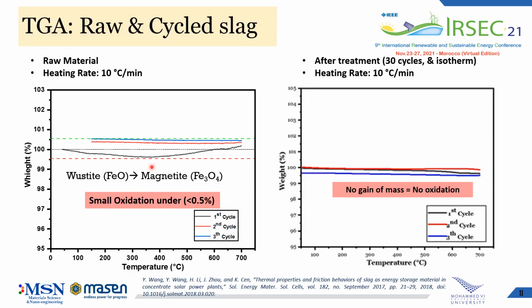And that was confirmed by TGA analysis, where we have a slight mass loss in raw material due to the evaporation of volatile compounds, followed by a gain of weight due to the oxidation of wustite phase. After thermal cycling, we didn't detect any significant gain of weight, and that means that we have no oxidation, therefore the material can be considered thermally stable.